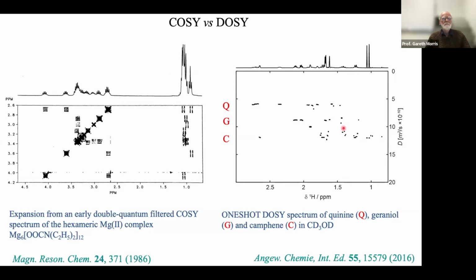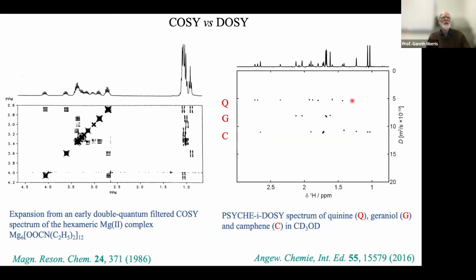If we compare this DOSY spectrum with one measured with a pure shift technique, which is where we basically just suppress homonuclear coupling effects in order to get a nice simple spectrum, we greatly reduce spectral overlap, and now we do see our signals grouped nicely according to molecular size. We've got the big quinine, the small camphene, and the in-between geraniol. But even now, these peaks aren't completely lining up. You see, they're slightly out here. That one's a little bit low, that's a little bit high. In DOSY, peaks don't necessarily appear in exactly the right position, and indeed we shouldn't expect them to.